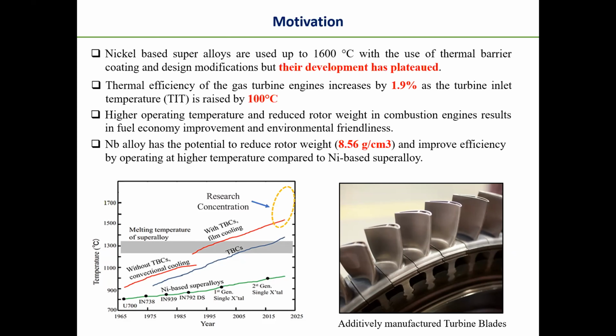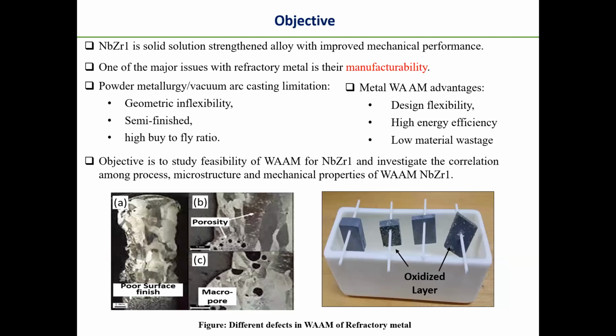So niobium-based refractory alloy has great potential to replace the nickel-based superalloys. But one of their major issues is their manufacturability, because generally powder metallurgy or vacuum arc casting are used for the manufacture of the refractory alloy, but they don't provide geometric flexibility and they're semi-finished. Lots of machining needs to be done, which results in a high buy-to-fly ratio.